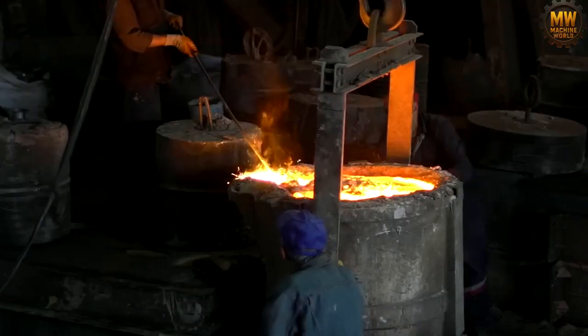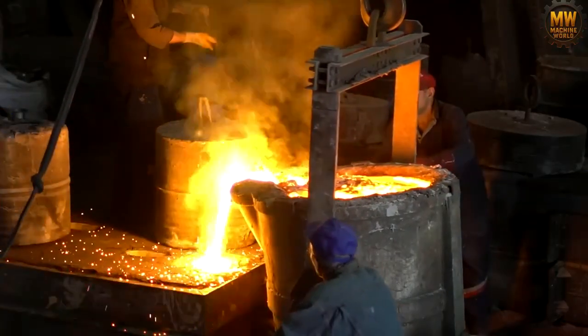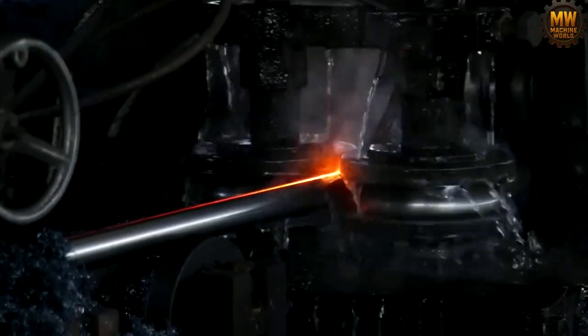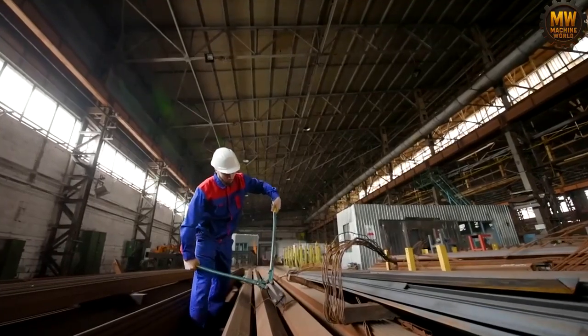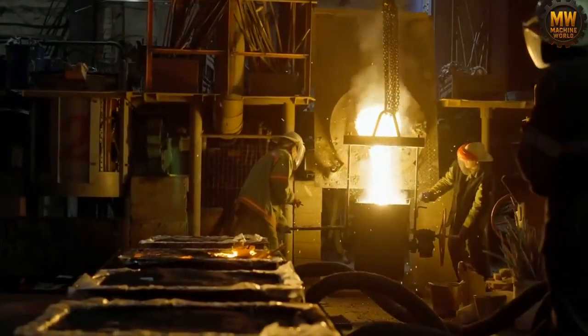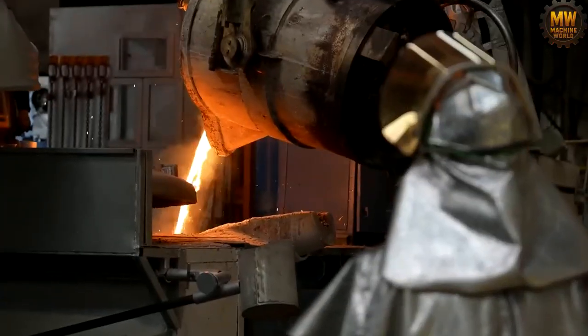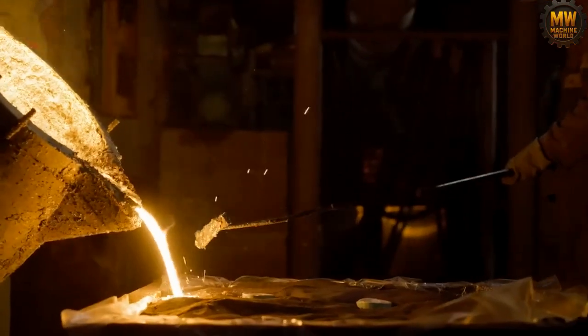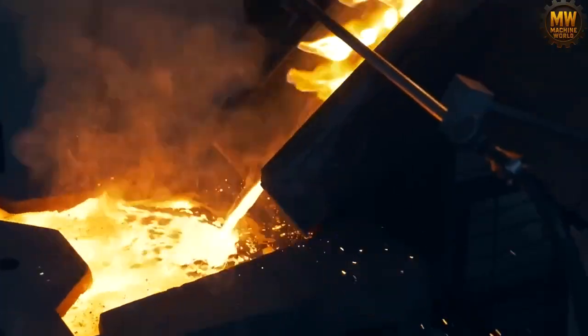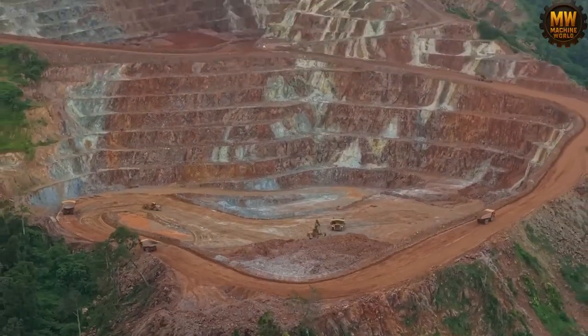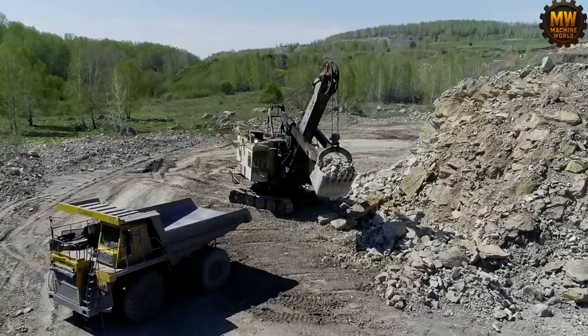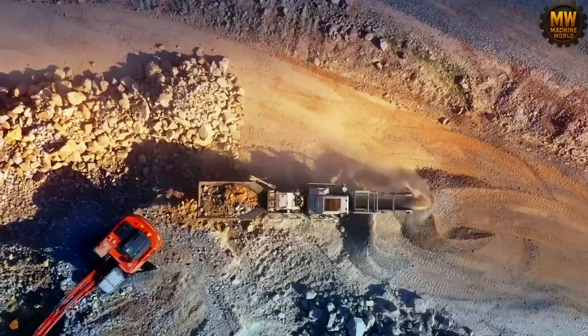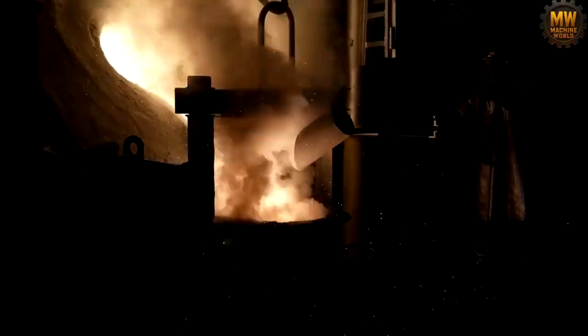The perimeter freezes instantly. The core remains dangerously hot. Industrial torches slice the continuous glowing extrusion into precise square billets. Casting these heavy solid blocks permanently locks in the perfect chemical alloy. But this is merely a raw blank before the main physical trial. To continuously feed the 1,600-degree inferno of the arc furnaces, mining crews must dismantle entire mountains day after day.